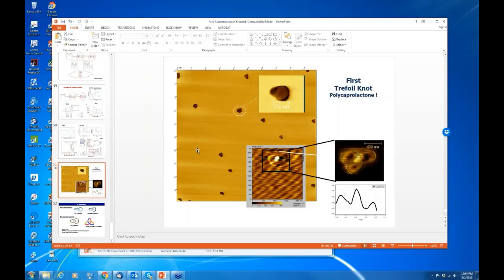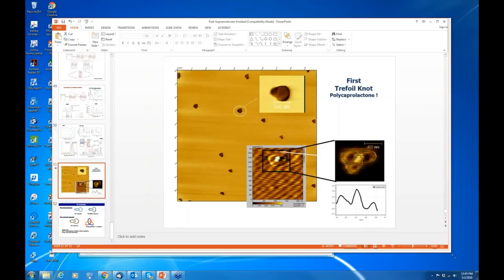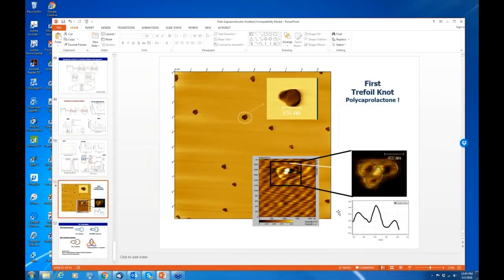A follow-up question: looking at the inset image zoomed in, we're wondering if the gradations — the lines underneath the trefoil knot — are the lattice structure of the mica. I would like to say so, but I would add that there's a component where the imaging method is not optimized. One can do some type of Fourier transform analysis or subtraction to get a better representation. We can probably do a better job with a sharper tip, better AFM, or better substrate preparation.